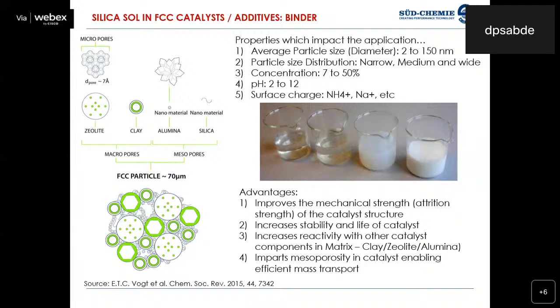If you see the matrix of this FCC particle, there are a couple of constituents which make this FCC additive, or FCC catalyst in general. One part is zeolite, the other is clay, the third constituent is alumina, and the next is silica. And normally when we mention silica, it is nothing but the silica sol. Silica comes from zeolite, silica comes from clay, and there is a dedicated source for the silica, which is coming from the silica sol.